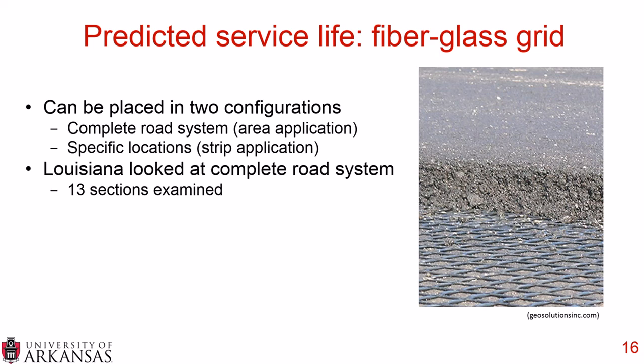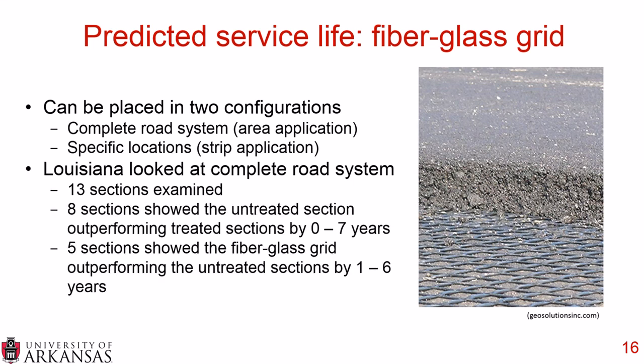Now, the Louisiana study only looked at the complete road system, and they looked at 13 different sections. And they found that 8 of those 13 sections showed the untreated section outperformed the treated section anywhere from 0 to 7 years. And they also found that 5 sections showed that the grid outperformed the untreated section by 1 to 6 years. So you can see this is a pretty big mixed bag. Some of the untreated sections outperformed the grid section by 7 years, but some of the grid sections outperformed the untreated sections by up to 6 years, and some showed no difference.